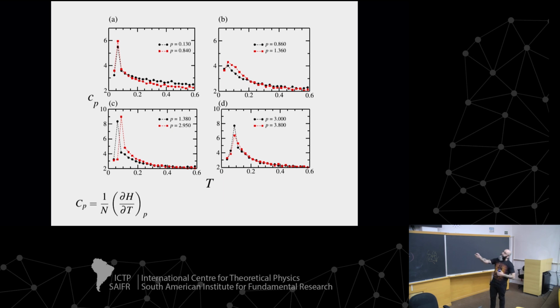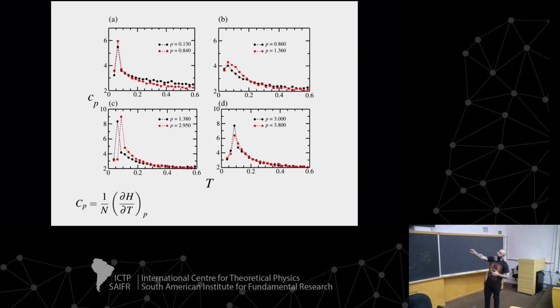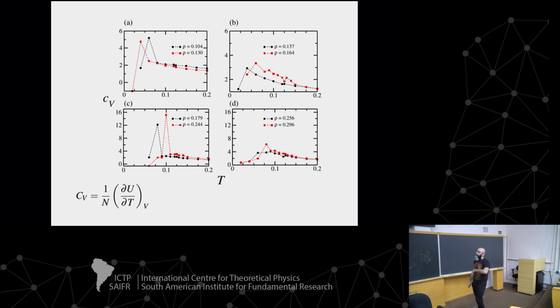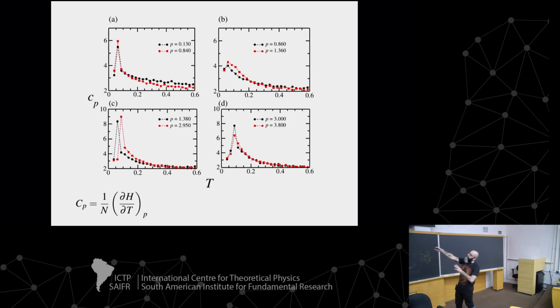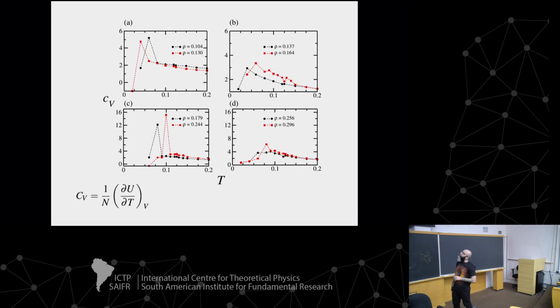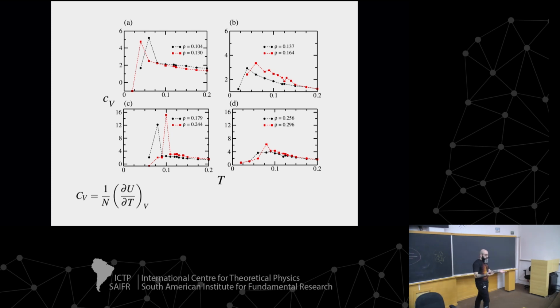So we can see, for instance, that in some cases you have a huge discontinuity in the CP, and in another case it is not exactly a discontinuity, it's more like a maximum. In CV, we saw the same kind of thing at almost the same temperature. Here it is around 0.1. Here it is also near 0.1 for the same density and same pressures. What is nice is that the NPT simulations we did using a package called ESPResSo, and the NVT simulations we did using the same program that Leandro and I worked with in 2010. And you know that that code was right. So we can compare both.